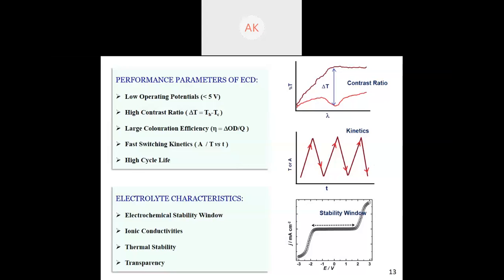Now, if you see the plot on the right-hand side top, what you mean by high contrast ratio is when you take the transmittance of a colored film, it is the red line. When you take the transmittance of the same film in its bleached state, it is the brown line. So the difference is delta T, that is the transmittance between the bleached and the colored state. This contrast ratio should be high enough so that it is perceivable by the human eye. Large coloration efficiency is when this color change occurs with minimum charge intercalation.